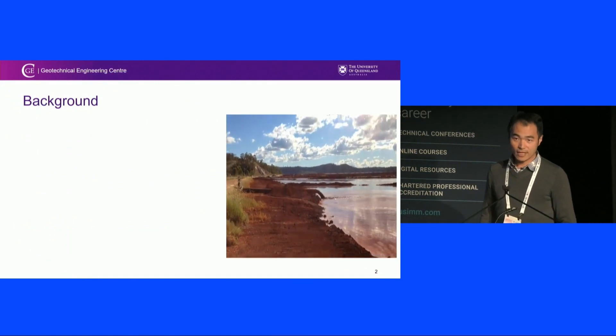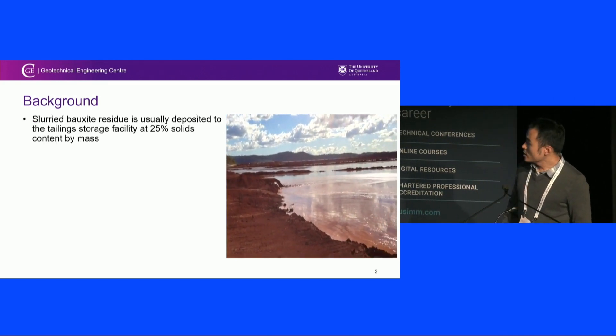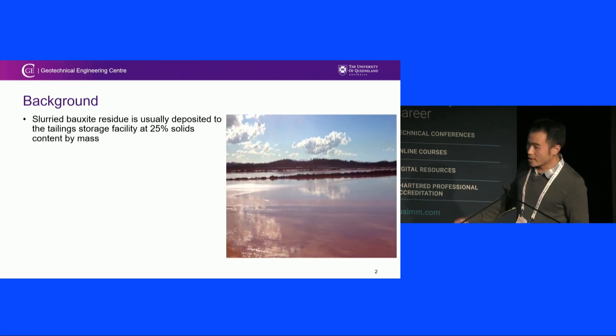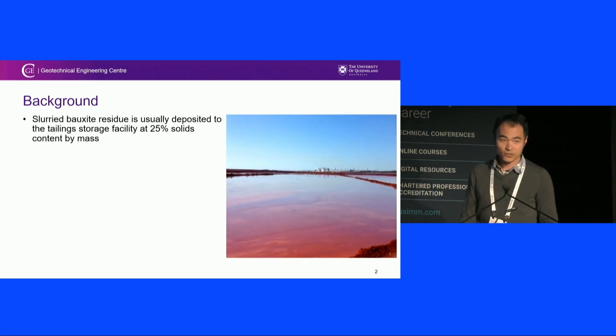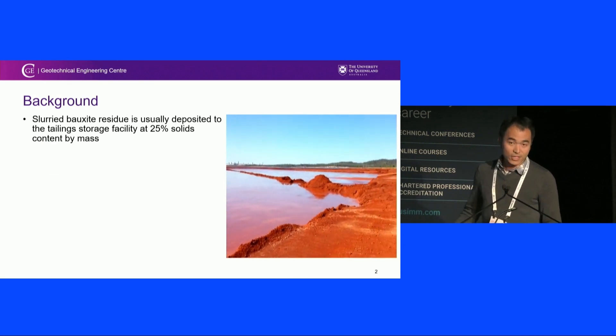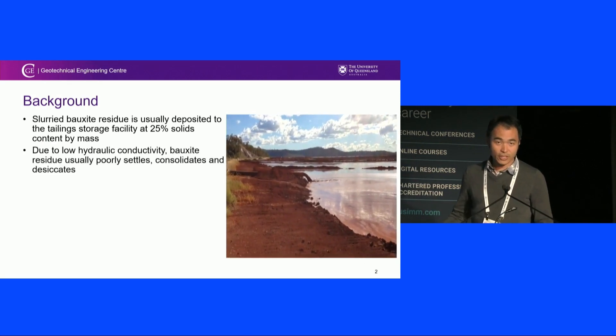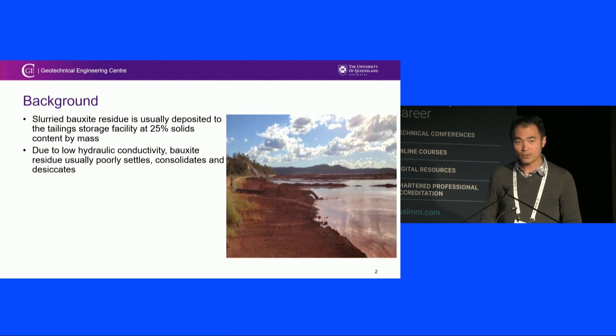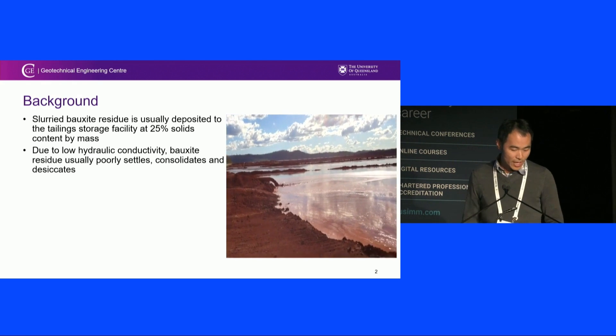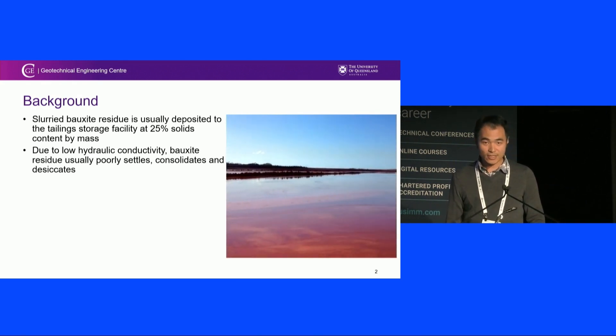The background of the project is about bauxite residue. It's basically a waste after a Bayer process that produces alumina. It is usually transmitted to a tailing storage facility as a slurry with 25% solids. Because it's fine material and it also has very low hydraulic conductivity, the settling process is very slow and the consolidation is also very poor because the low hydraulic conductivity dissipates the excess pore water pressure poorly.